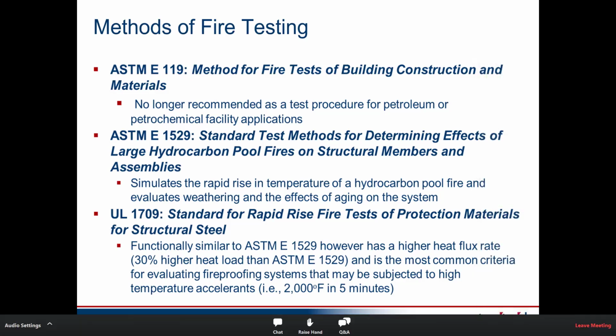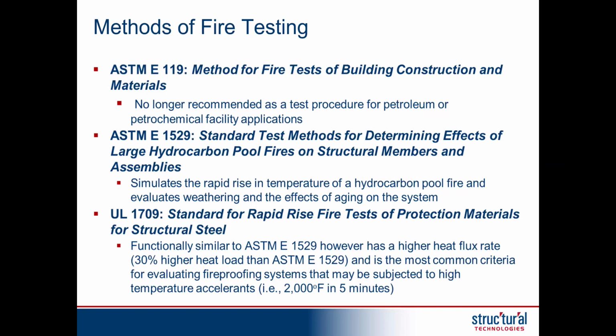Now, what is accepted in the industry right now worldwide is essentially Underwriters Laboratories test UL 1709, which is set up similar to ASTM E1529. There's a 30% higher heat load with the 1709 versus the 1529. And what's special about these tests is it also evaluates the weathering and the effects of aging on systems. So to get a successful UL 1709 test result is very important for manufacturers of these fireproofing materials. And if you're a specifier in the webinar audience, it is very important that you look to see that they have a UL 1709 rating on the fireproofing materials if it's going to be used in a petrochemical facility.